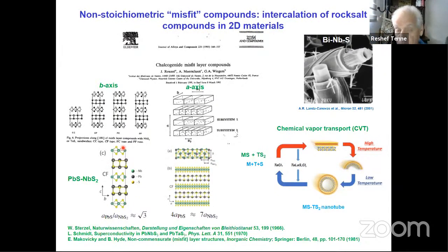What we have done is that we have used the concept of Pauling, which stated that in such a situation, the layer will naturally fold, and indeed it folds. If you use smart chemistry, you can close it from a folded structure into a nanotube. That allowed us, in a very short time, using chemical vapor transport, to get many, many nanotubes from misfit layered compounds. There are hundreds, if not more. Now we make them from alloys, quaternary, and the number is unlimited because you have alloys in different compositions.